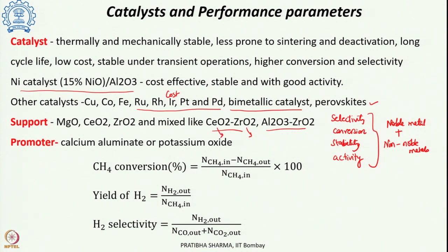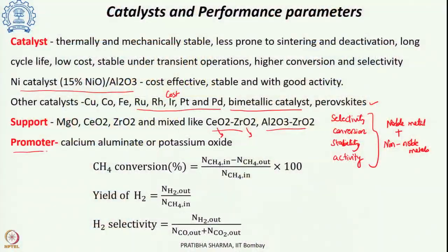So, that way there can be a mix of these oxides to act as a support, and the support serves various purposes here. It can stabilize the catalyst, it can provide the required surface area, it can provide the dispersion of the catalyst, it could reduce the coking and sintering by having an interaction with the catalyst, and it could provide the required basicity. So, there are several purposes that the support can serve here. A small quantity of promoter can also be added, and that reduces the coke deposition, like calcium aluminate or potassium oxide.